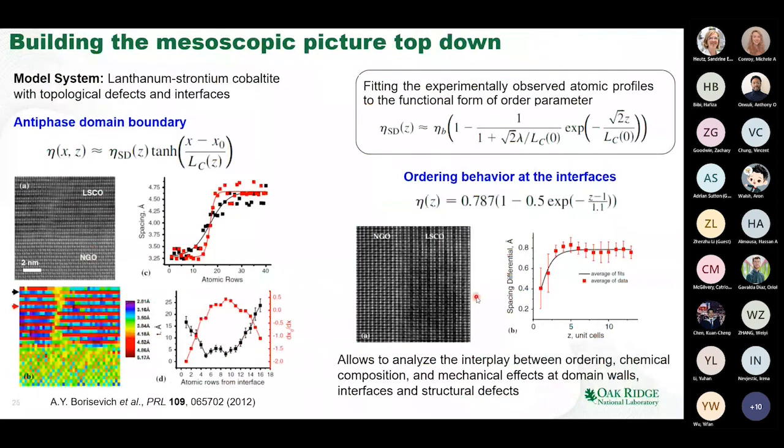That's actually where my fascination with electron microscopy as the tool to study nanoscale systems started from. It turns out that if we observe something like an antiphase boundary in the vacancy order system, or the interface between the ordered and high symmetry phase, we can simply take the analytical solutions from the Ginzburg-Landau theory, which contain some number of unknown parameters, some form of correlation lengths or screening lengths, and we can just match this solution to the experimental observation. So then we just extract it from the microscopy data, and it is either very difficult or virtually impossible to get it in any other way.